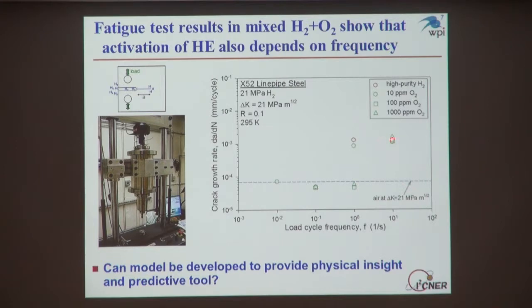So for example, the circles are 10 parts per million oxygen, and these crack growth rates come down to the rates in air at a frequency between 0.1 hertz and 1 hertz. This is interesting scientifically, but also technologically, because a lot of the hydrogen containment components that would be operating, let's say a pressure vessel at a fueling station, are going to be pressure cycled very slowly. And so if we do have some of these oxygen impurities in our hydrogen gas, we could account for the possibility that the oxygen is slowing down the crack growth rates, and we can do a more reliable life prediction.